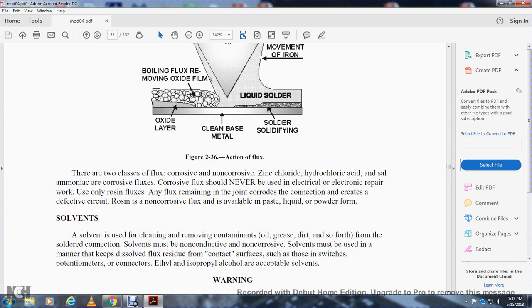Zinc chloride, hydrochloric acid, and sal ammoniac are all corrosive fluxes. Corrosive flux should never be used in electrical or electronic repair work. Use only rosin flux, because remaining corrosive flux on the joint will corrode the connection and create a defective circuit. Rosin is a non-corrosive flux available in paste, liquid, and powder form.